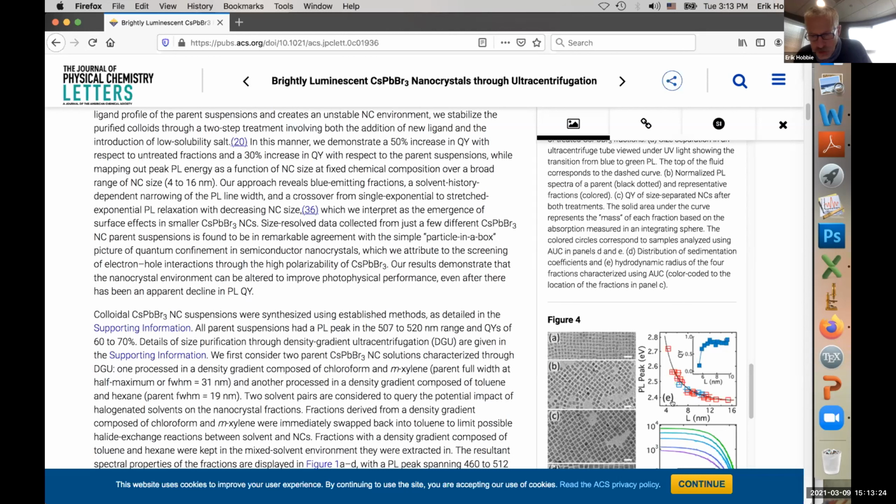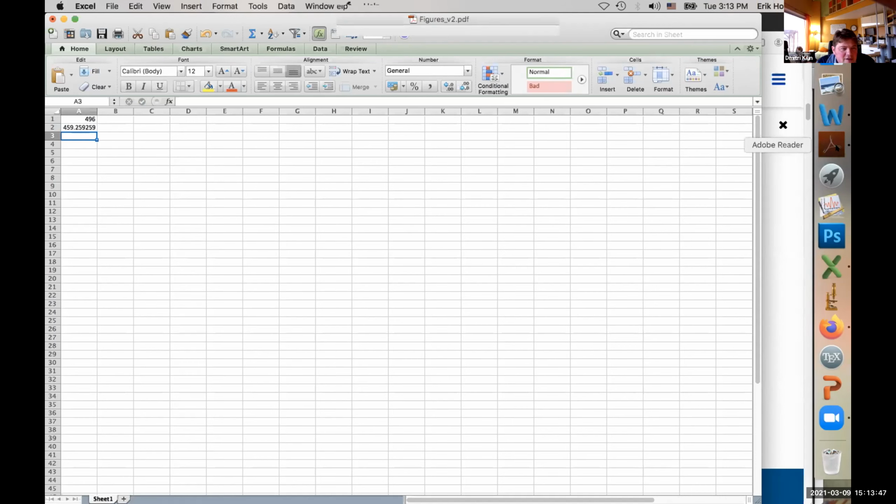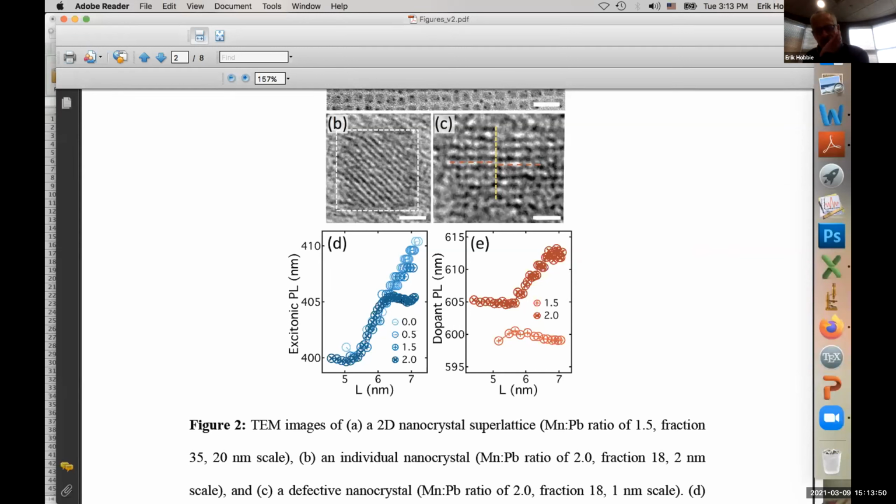So let's just do a quick calculation here. Going from 6 to 4, you're talking about going from 2.5 to 2.7. Okay. You're talking about a big shift, right? That's your point, right, Dmitri? Yes. So back to here, that would seem to suggest that this really isn't confinement, right? Or it is not. If it is analogous to confinement, it's some, I don't know, light version of confinement.